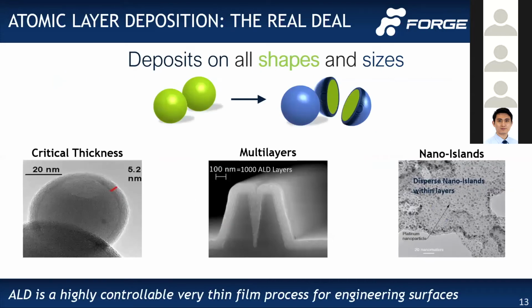This is what it really looks like once you get to the images. The one on the left is a non-porous particle, conformal uniform coating, 5 nanometers thick. That's probably not what you'll end up doing in catalysis, but the one on the right might be—that's platinum deposition onto an oxide surface. We'll talk more about which one, left or right, might be the most commercially viable application. But again, particles there in that image, that's what we focus on at Forge Nano.